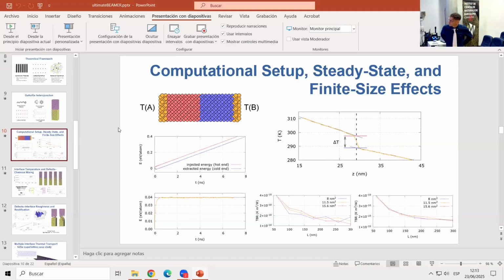So here in your profile, we see a clear linear trend, but then we see this non-linear temperature profile, which is standard to simplify just using the Kapitza expression. So I characterize a delta T, and the heat flux is proportional to this delta T. Of course, this is phenomenological, but do you think the Kapitza understanding of this effect is capturing the true physics that is going on here? I mean, in terms of the constitutive equations that would relate the heat flux to the temperature profile, do you think that we need something beyond Kapitza to fully describe this, or you think that we should only rely on MD and forget about it?